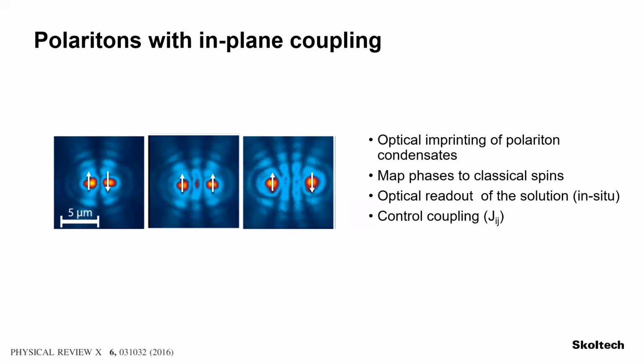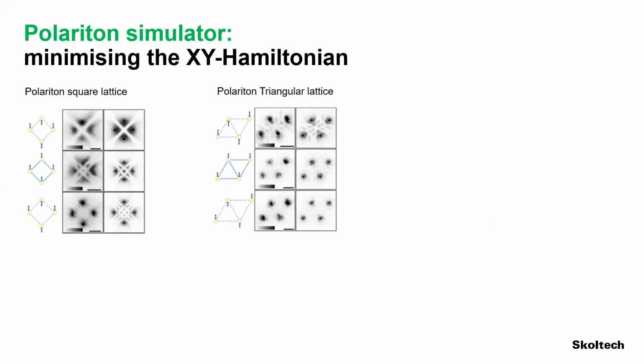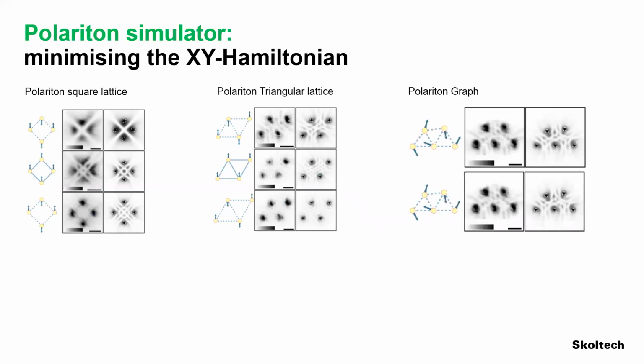So this is what we did. Back in 2017, we created different lattices, experiment and theory, of polariton condensates, and we found out that actually, when they condense, the phases will arrange in a way that minimizes the XY Hamiltonian. So at threshold, they will not have just 0 or pi phase. If I create a graph, an irregular arrangement of the condensates, the phase configuration will minimize the XY Hamiltonian. So we were very happy with that, because then we could take this and apply it to real-world problems.